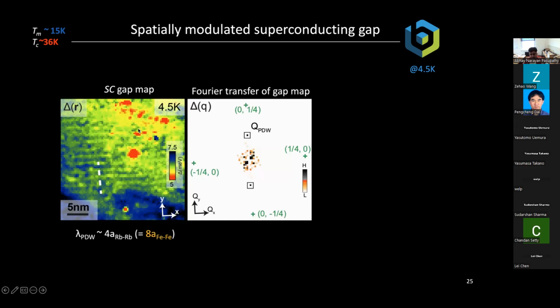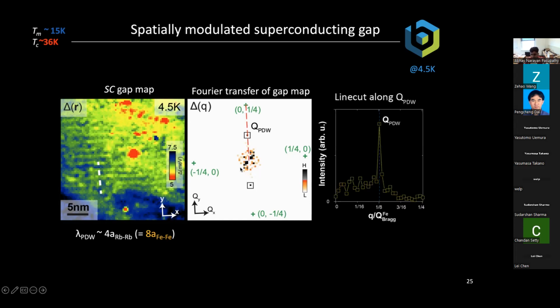And if you take a Fourier transform of this, you can see very clear spots, which tells you the wavelength of these stripes. And the wavelength of these stripes is, as I said, approximately 8 lattice constants. And it's a beautiful long-range order. So we've seen many dozens of periods of these that have coherent modulation. So it looks like cosine of QR without phase slips. Yeah, so this is a line cut of this Fourier transform. You can see this peak, which is basically single pixel sharp, telling you that it's a nice, well-defined wavelength in the system.